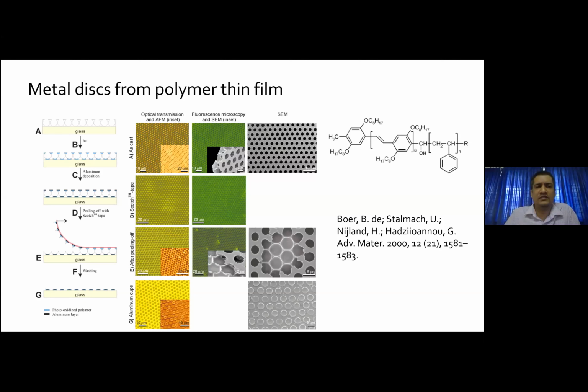The R group is not varied, actually. It is what is called the growing chain end. This polystyrene is made by nitroxide mediated polymerization. The R group is the free radical, the growing chain end, and so on. If you see the NMP method of polymerization, you will know that the NMP will be locked into the chain end as a transition or in-between state.